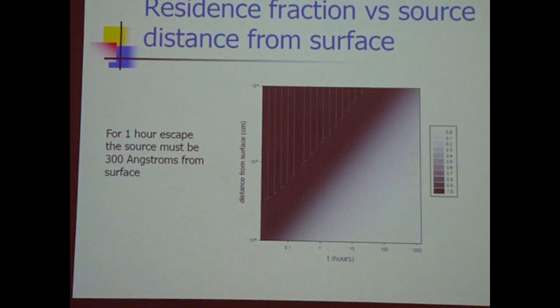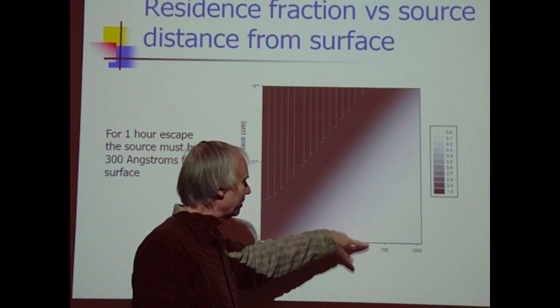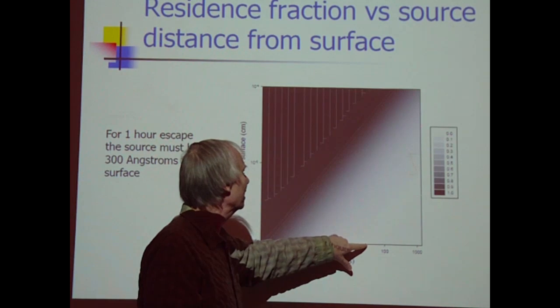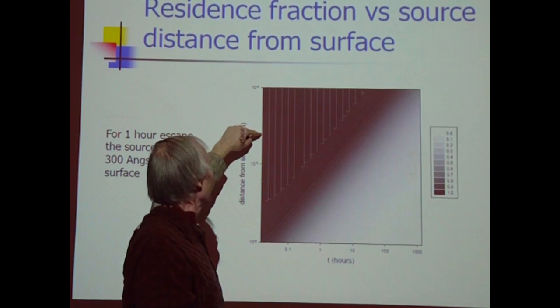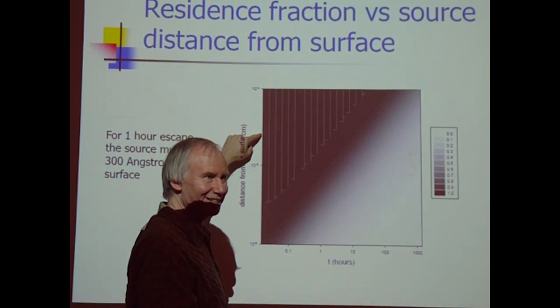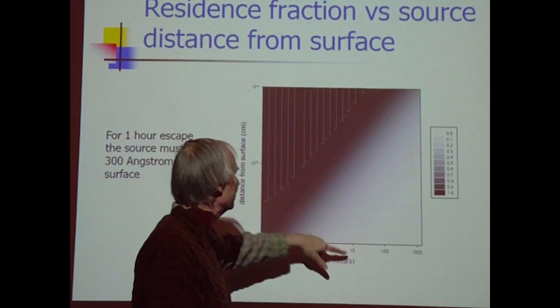So I look at this, and I'm thinking that, if I want to do a measurement of helium-4 production in the gas phase, if the gas comes out reasonably fast, and if it has to diffuse from the point where it's made out to the surface, then by figuring out how long it takes the helium to come out, I can go ahead and put an upper limit on how far in from the surface it was. In Godsey's experiment, I don't remember the time axis, but it was measured in units of hundreds of hours. So in Godsey's experiment, the resolution was around here, somewhere here. So I go here, and I say they got maybe half of it out, then I'm up here. If I go over here, I'm talking about maybe 2,500 angstroms in from the surface. And that's not a lot. In some of the other experiments, the numbers are here.